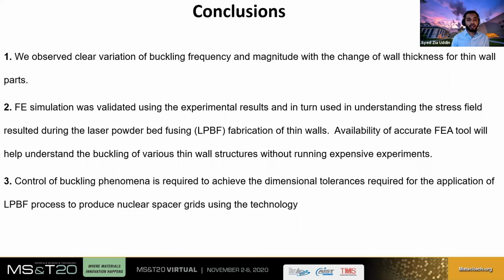the nuclear industry. And then we also calibrated our finite element simulation package for predicting the buckling in this highly nonlinear environment in the 300 micron and 500 micron wall thicknesses. We're still working on getting the 200 micron wall thickness simulation right. And it will be part of our future work that we're going to try to use this simulation to get more physical insight into the problem of buckling in thin wall structures and use them not only in spacer grid fabrication, but everywhere thin wall manufacturing is required.